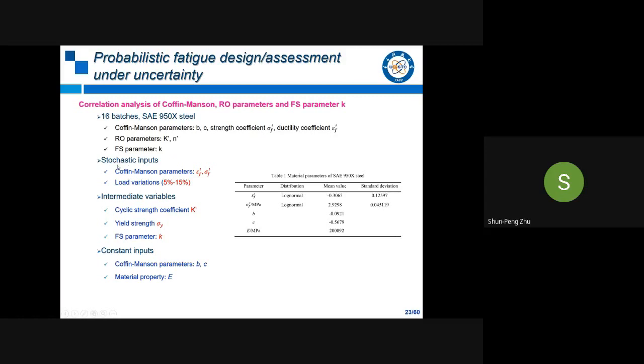And about the inputs with the stochastic, we choose which part. Actually, we need to clarify the correlation between these seven parameters, and also some earlier tests for some parameters like B and C. They are almost treated as a constant. So here we choose these three as the stochastic inputs, the median variables like K prime, the cyclic strength coefficient, yield stress, and also the normal stress sensitivity parameter K. And for the constants here, we chose these three. So these are the inputs for this analysis.